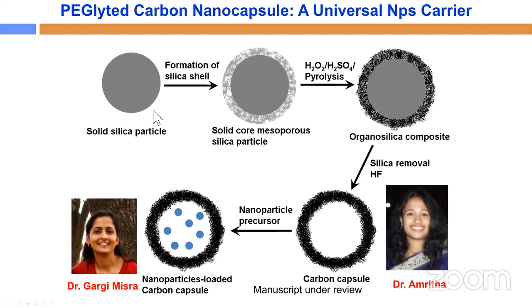For this carbon capsule, they have taken a solid silica particle, coated with mesoporous silica, which has a carbon precursor. We then do the pyrolysis, and all the carbon precursor converts into carbon. Remove the silica, and you get the carbon capsule. Then put it into the nanoparticle precursor like earlier, under hydrothermal conditions, even up to 300 degrees centigrade. All the different types of nanoparticles can be loaded.